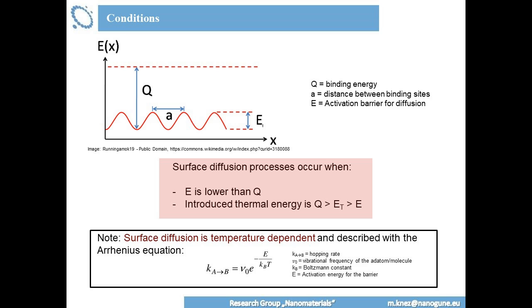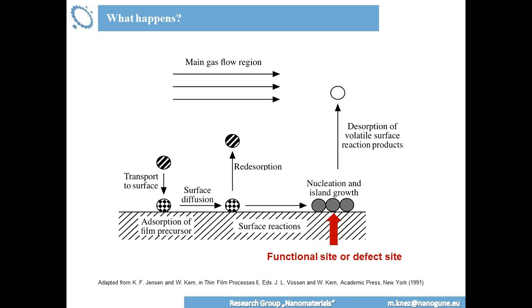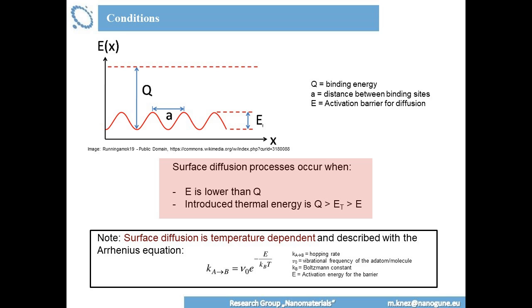This is something which is not new, and I think it's very easy to understand, especially from the physical point of view. Many of you have learned about STM, AFM, and so on. Many people do STM investigations on surfaces with atoms deposited there of one material on top of another, investigating Kondo effects and whatever, impurities. And they do this at really low temperatures. And the reason for those low temperatures is, if you deposit an atom on top of the surface, if it's only physisorbed, so not chemically bound, it will diffuse on the surface in case that you exceed the activation energy for diffusion. So the STM people need to stay at a very low temperature in order to freeze the diffusing molecule.